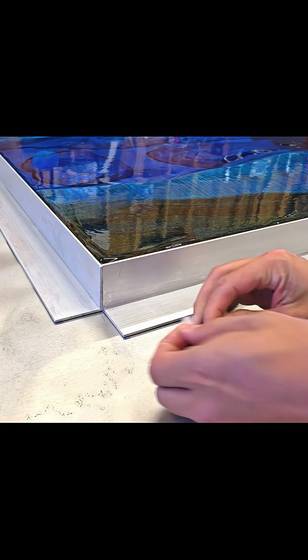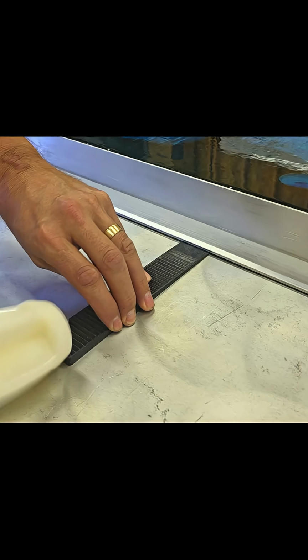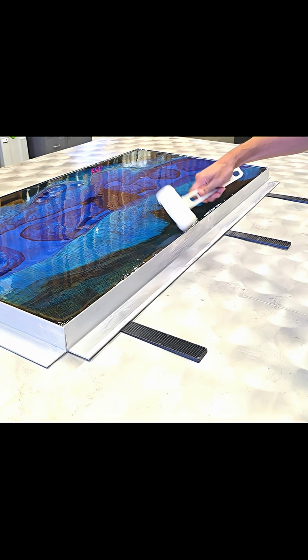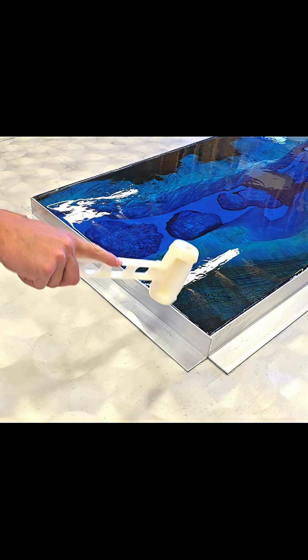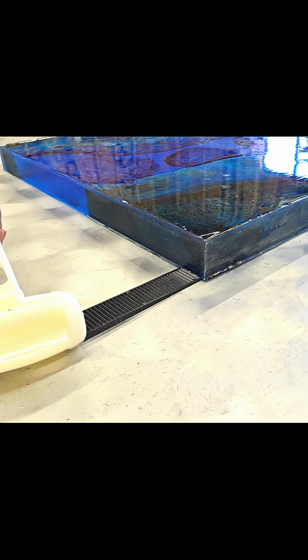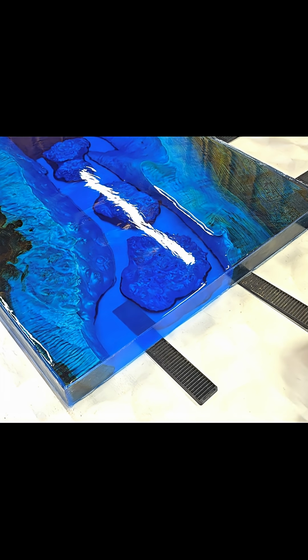As the resin continued to cure, the temperature came back up but never reached over 95 degrees again. The pour table was a success. The silicone and the dams easily separated from the pour table and the resin table. With a few shims, I was able to separate the whole table off from the surface.